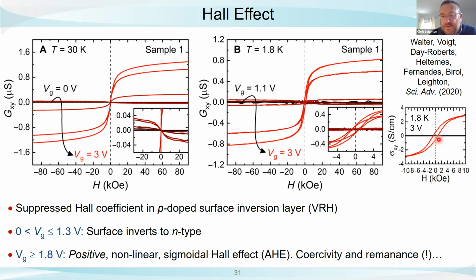If I plot just one curve for you here at 3 volts, 1.8 Kelvin, it looks like a very nice anomalous Hall effect of a ferromagnetic material. And I have to emphasize that it is a positive anomalous Hall coefficient, which is the same sign as we get in bulk cobalt-doped iron disulfide. So you have a nonlinear sigmoidal shape Hall effect. It has the right sign. You have finite coercivity, you have finite remnants. It really looks like you've been able to induce ferromagnetism, okay?